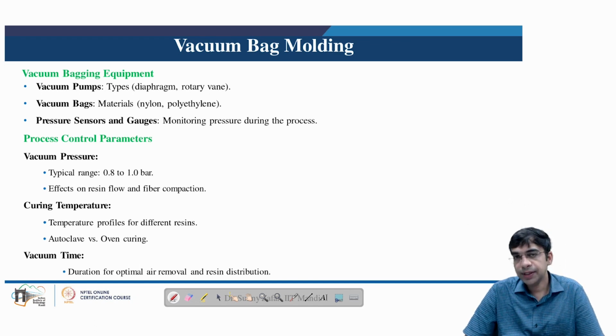The vacuum bag may also consist of certain pressure sensors and gauges to continuously monitor the in situ pressure during the curing process. Typical process control parameters in vacuum bagging involve a typical pressure range of 0.8 to 1 bar. This affects the resin flow and fiber compaction. Curing temperature can be different, with different types of temperature profiles used for different types of resins, and there is also a trade-off between what temperature is being used with an oven or an autoclave, as both systems act in a different way. Vacuum time is the time for which the vacuum is applied, and this ensures optimal air removal and resin distribution.